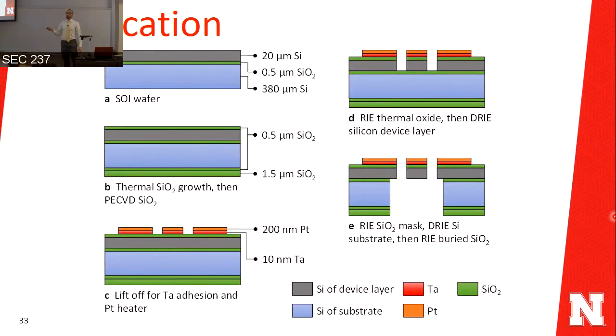The first step of microfabrication is to add a dielectric layer of silicon dioxide on top and bottom of the wafer to insulate the platinum heater, which will come next. And we have made this silicon dioxide through wet oxidation in a furnace at 1100 C. We deposited another layer of silicon dioxide by plasma-enhanced chemical vapor deposition, and this will work as an etching mask while we release the device.